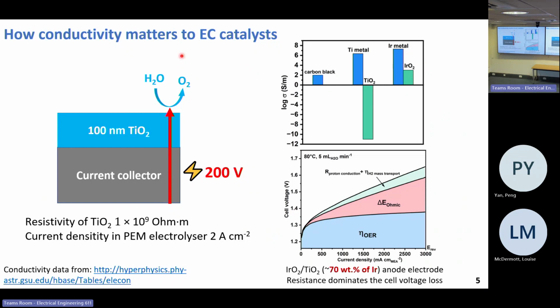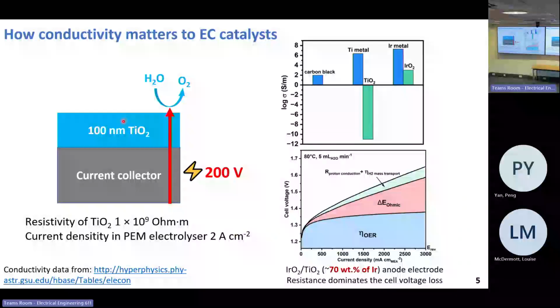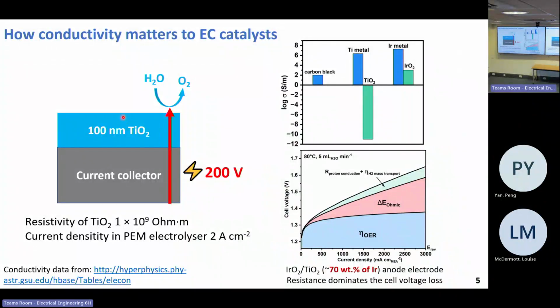The porous transport layer in PEM electrolysers is made of titanium mesh. So if you accidentally form 100 nanometers of titanium dioxide, and considering the very high current density in PEM electrolysers, you will need an extra 200 volts to break through this oxide layer. The thermodynamic water splitting voltage is just 1.23, so there's no way for titanium dioxide to be a good electrocatalyst.